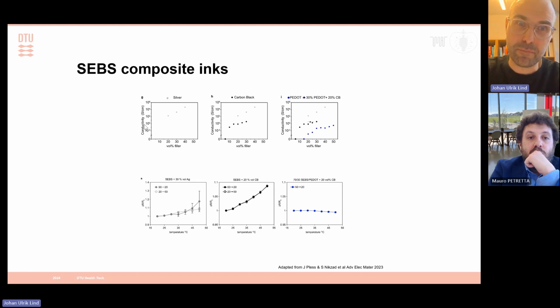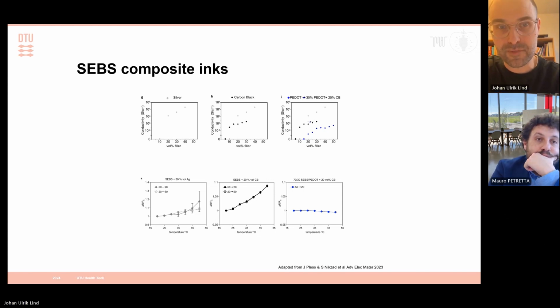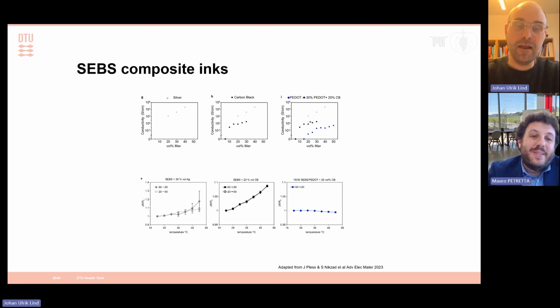But you get less bang for the buck, you could say. You get increasing conductivity every time you increase the amount of particles loaded, but it's also more expensive, you could say. The silver is expensive. But then there's also the mechanical properties. I didn't include the data on this slide, but obviously, as you add more and more filler to these elastomer inks, we decrease the stretchability of the system. And that's very much dependent on the type of particle, is what we found in this study.